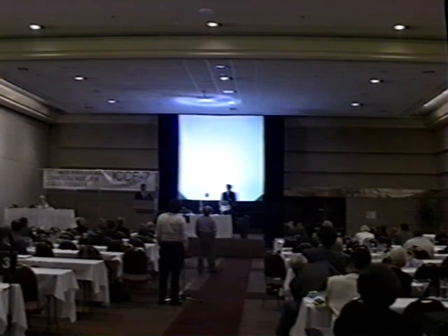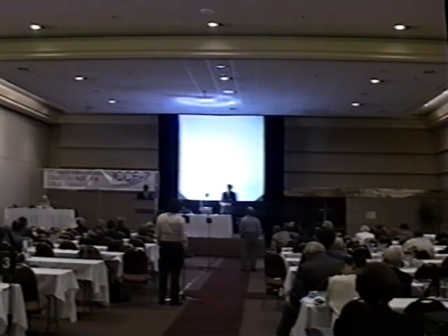Yes. Have you done any chemical analysis of that film afterwards? Yes, I tried with a micro X-ray analysis, but I found many elements that I used for the fabrication of the cell, but no difference in the zone with melted nickel and the zone with not melted nickel. No differences. But I found aluminum, silicon, and so on. The amount of material used is very, very low.